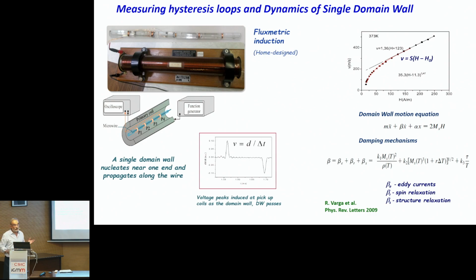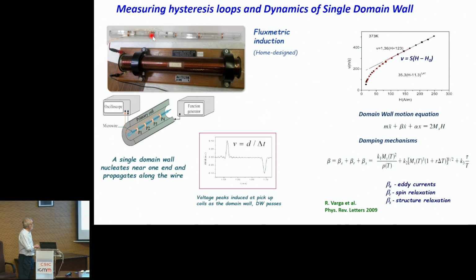Measuring the hysteresis loops of these microwires is apparently very simple. We apply the magnetic field along a solenoid, for example, and we have a number of pickup coils to obtain the time evolution of the magnetic domain wall I mentioned before. When the domain wall passes these pickup coils, we get a signal. So we have two subsequent peaks, and as we know the distance in time and the distance between the secondary coils, maybe 1 centimeter, we can get the velocity of this propagating domain wall. This is an experimental result for the velocity of the domain wall as a function of the applied field. We can reach up to around 1 kilometer per second.